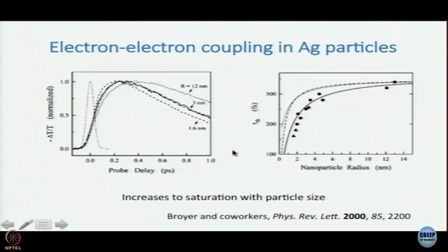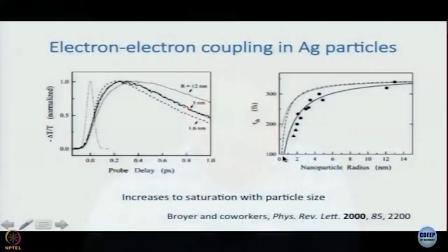So, this electron-electron coupling time was found to be, where is the electron-electron coupling time here? You are excited and then see there is a rise, right. Why is there a rise? Because equilibration has to take place among the electrons that are there. First you have done a quantum of excitation that has to get redistributed among all the electrons before anything else can happen. So, that comes up actually as a rise, and this rise time is found to increase from say 100 femtosecond to 300 femtosecond, the second plot, depending on what the nanoparticle radius is.